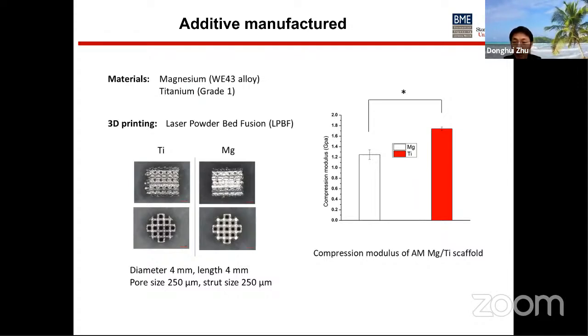Here is the optical imaging showing the titanium and magnesium cylinders with porous structure. The diameter is about 4 millimeters, length is also about 4 millimeters, but the pore size is 250 microns, and the strut size is about 250 microns. The compressive modulus of these two materials is around 1 to 2 gigapascal, with titanium a little bit higher than magnesium.